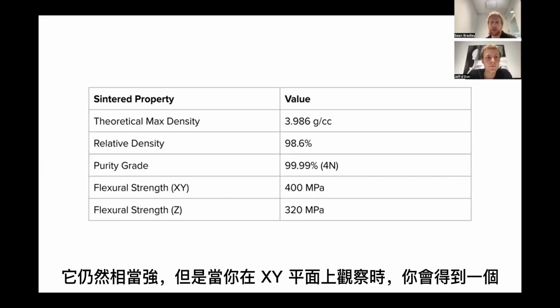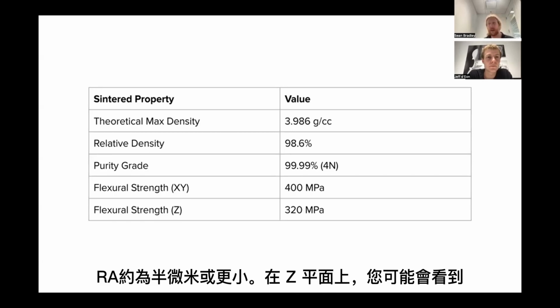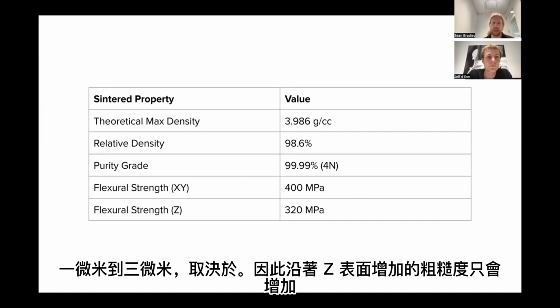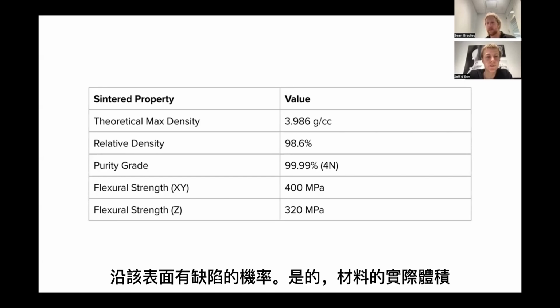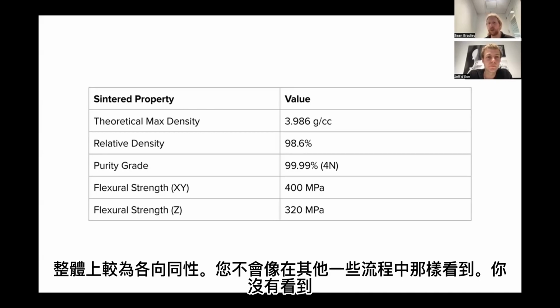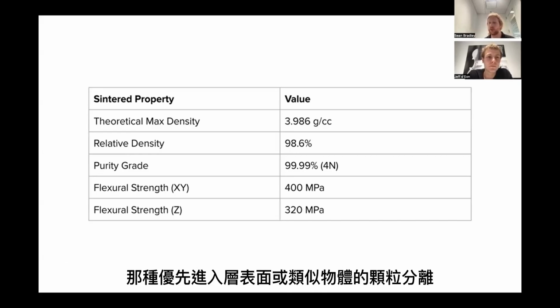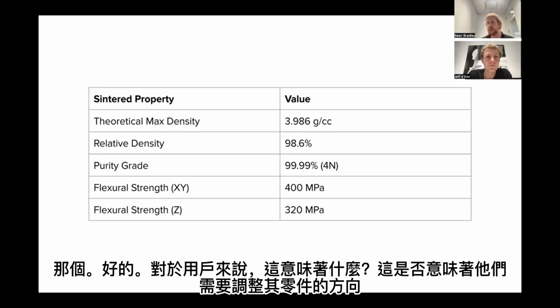It is still pretty strong, but when it's in the XY plane, you've got an Ra of about half a micron or less. And in the Z plane, you might be looking at 1 micron to 3 microns, depending. So the added roughness along the Z surface just increases the probability of having a defect along that surface. Yeah, the actual bulk of the material is overall a lot more isotropic. You don't see, like you would in some other processes, that kind of separation of particles that goes preferentially to layer surfaces or anything like that.